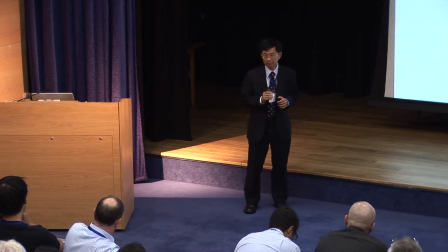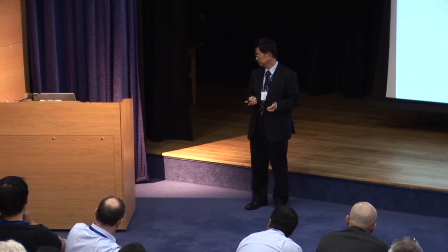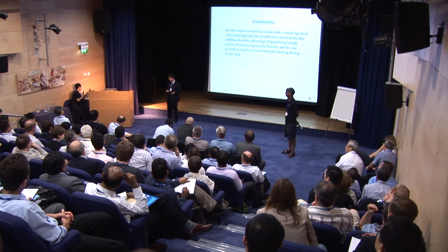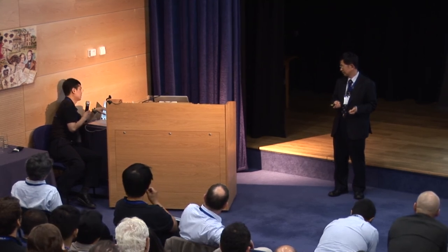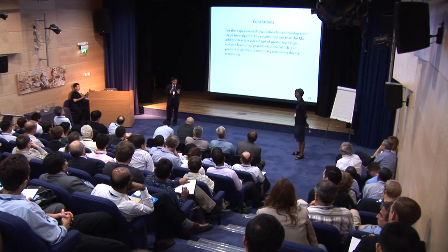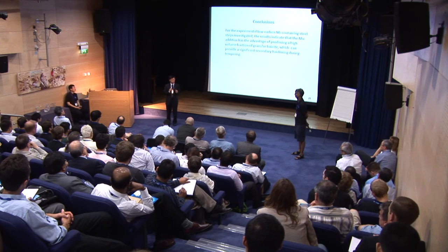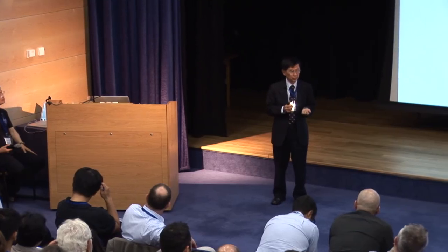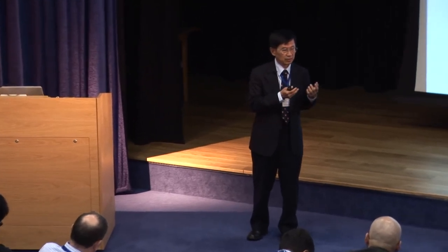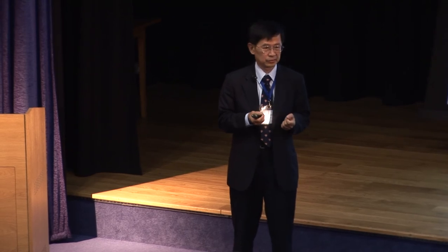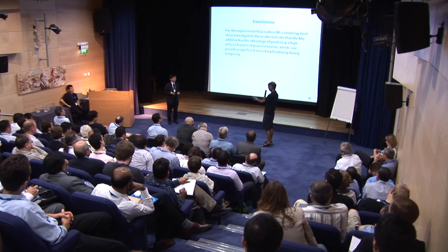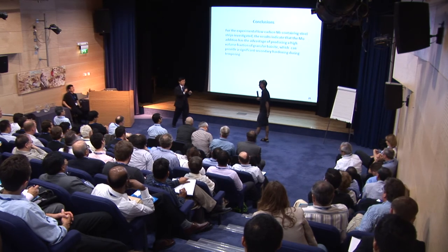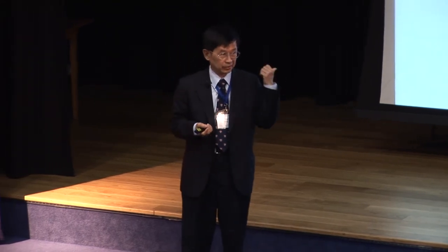Another question from Sujay. You say niobium increases the hardenability and you form granular bainite. How do you separate the ferrite and granular bainite? Because it's a low carbon steel, it's very difficult to get a complete bainite structure, so we always have some ferrite. That's the reason we need accelerated cooling and also microalloy addition. Those parameters are very important for us, so we just use trial and error to prepare this material. How do you distinguish the ferrite from the bainite? It's very easy, just by Vickers hardness. We can distinguish by Vickers hardness, and also through EBSD.